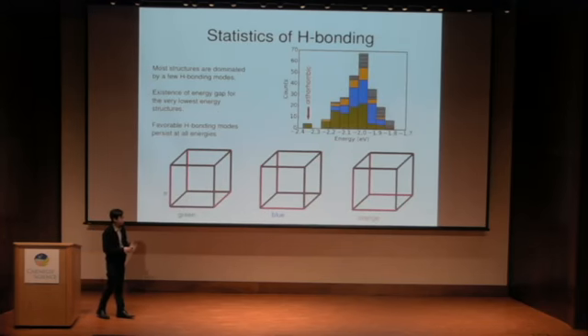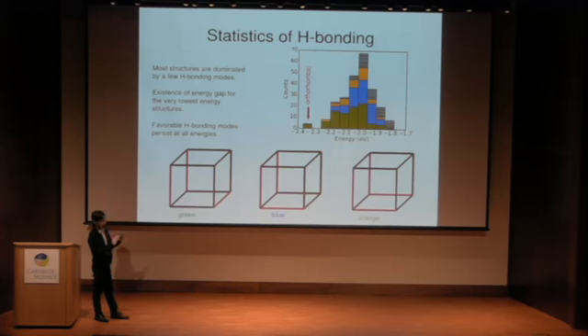Now let me explain results of DFT calculations. The way you read this histogram is like the following. I have many structures, and each structure has a certain number of bonding modes. For each bonding mode, I take the energy corresponding to that structure and put it in the appropriate bin. And what I find is that there is a predominance of 2 or 3 different types of bonding modes shown here. This type of bonding mode is all those counts labeled in green, these ones are the ones in blue, and these ones are the orange ones. These 3 are the main ones in the sense that they account for most of the bonding modes in my database. But there are some others which I've not labeled here, but these happen only at the higher energies.